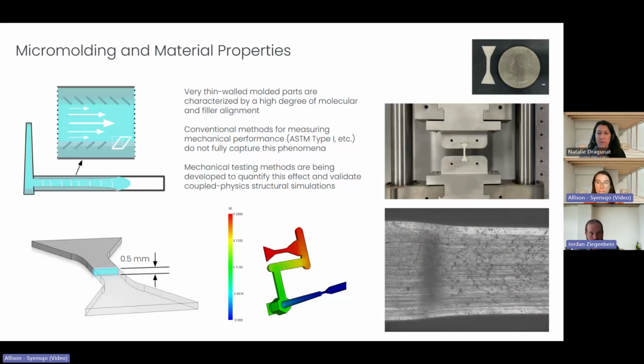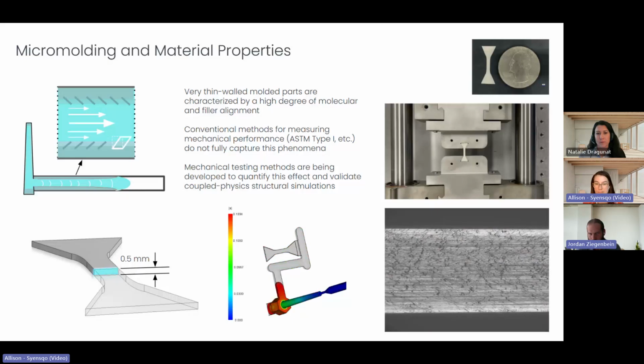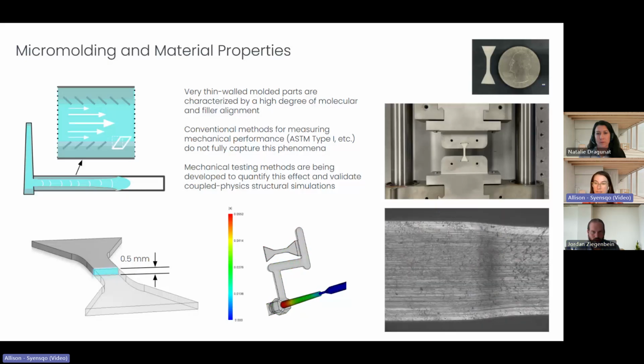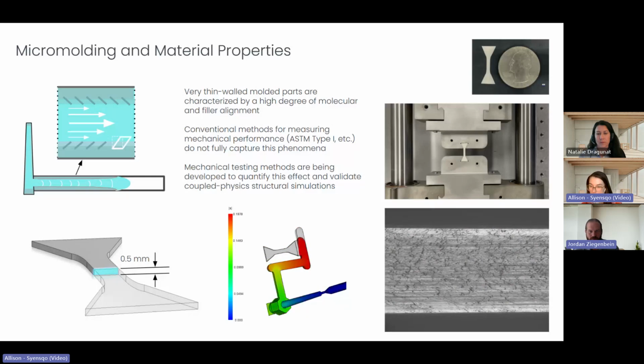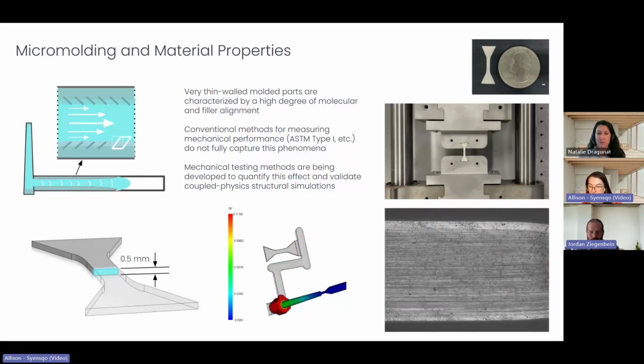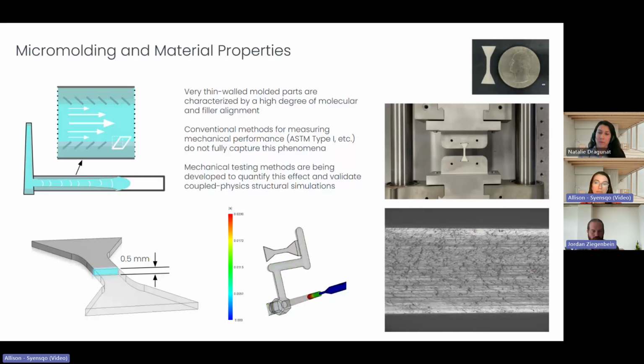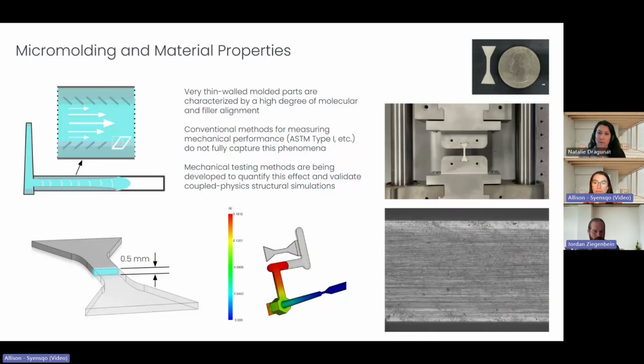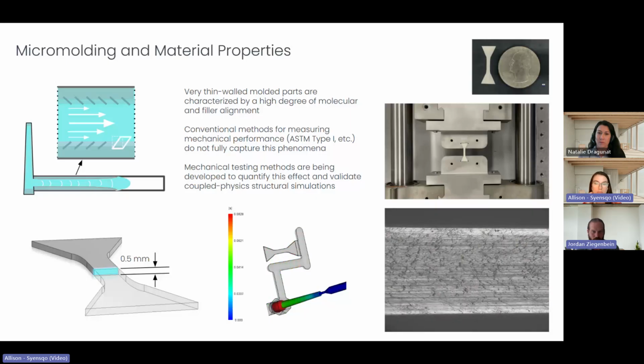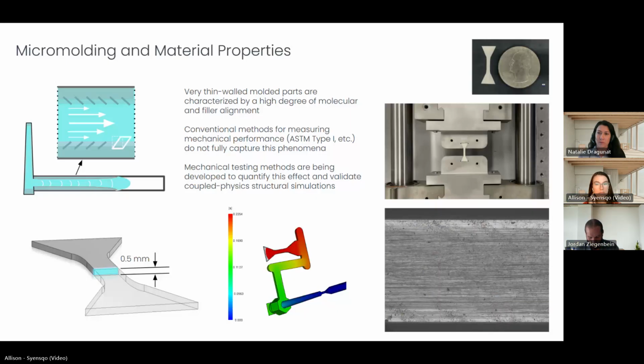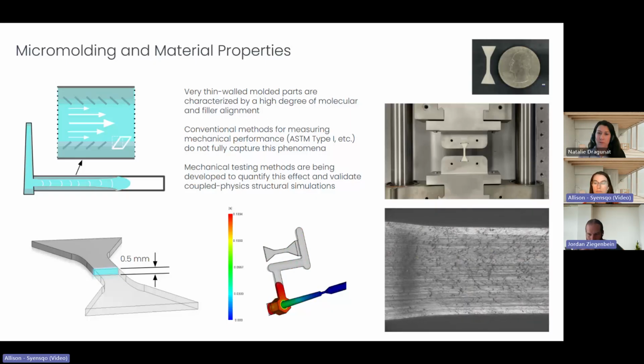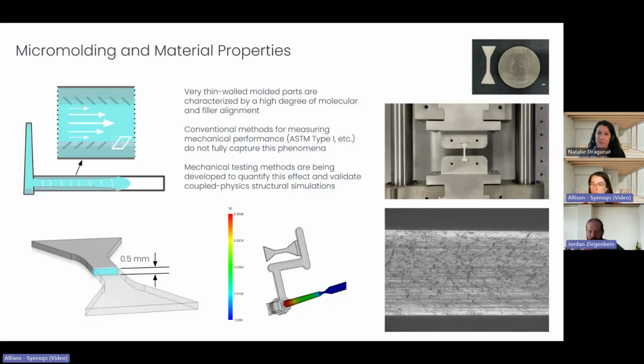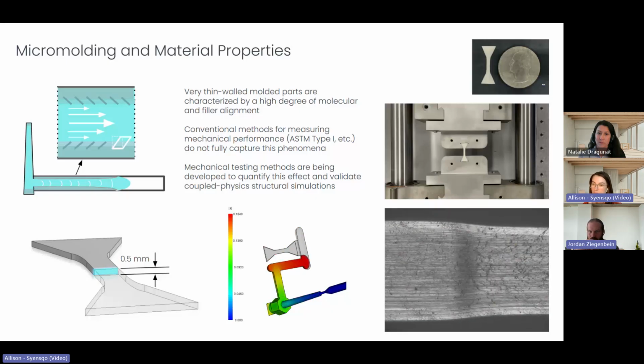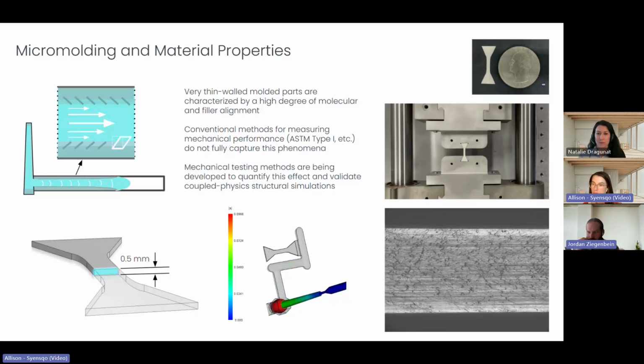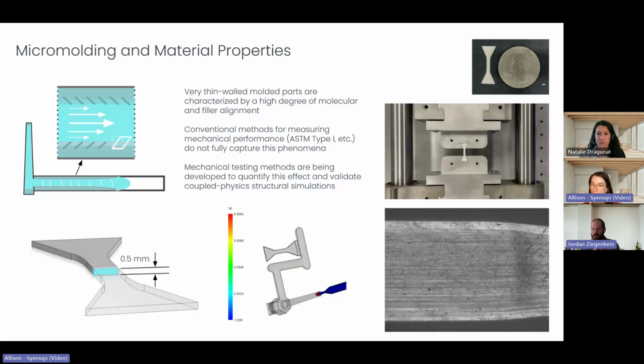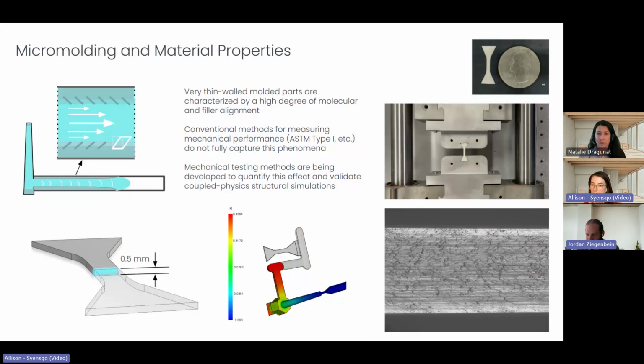So similar to how rheological behavior may be different at very small scales, we expect the same thing with the mechanical behavior. In very thin-walled molding, you can have higher degrees of molecular alignment. Cooling rates can be dramatically different than what you're used to. You won't capture those effects with a basic ASTM or ISO bar, for example. The example that you see in the bottom right-hand corner is actually one of our sulfone polymers. This tensile bar that's being tested has a cross-section of only 1 square millimeter. And we're actually able to see the necking region as it evolves and moves past on the camera.